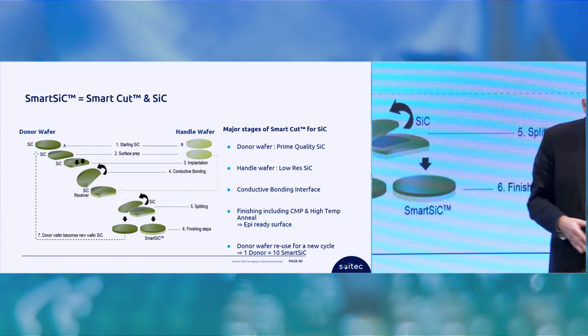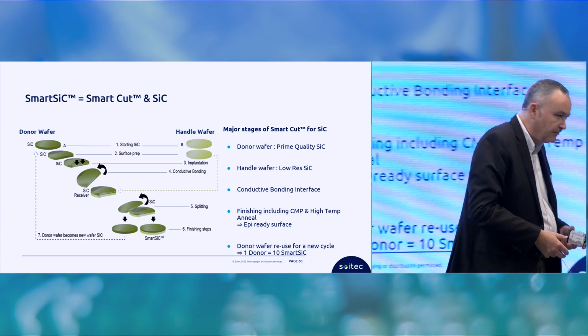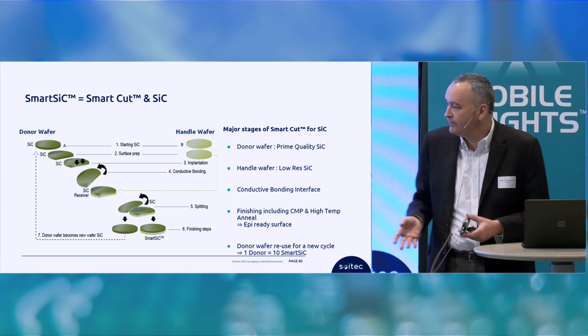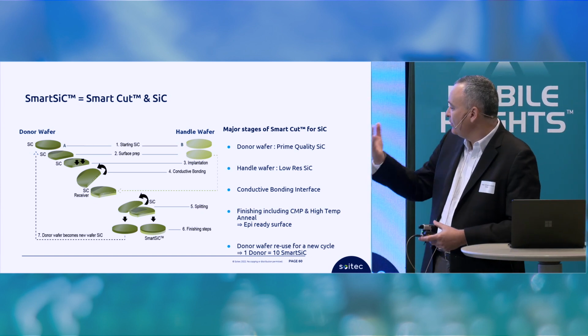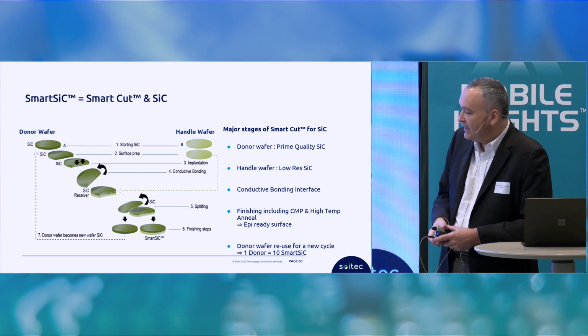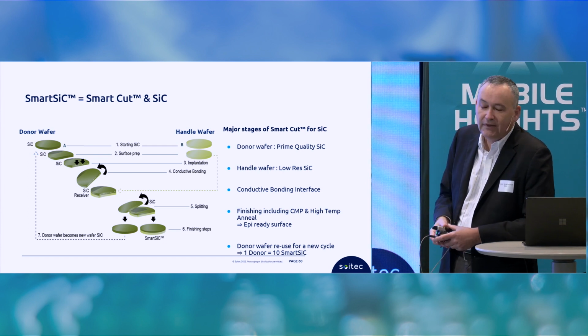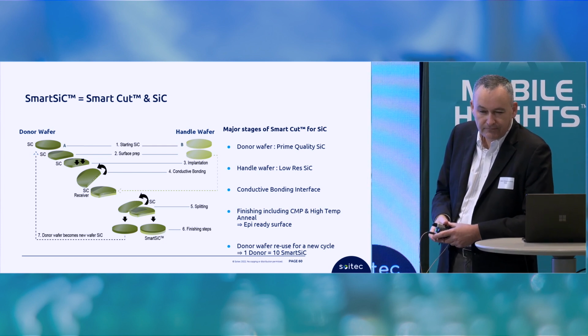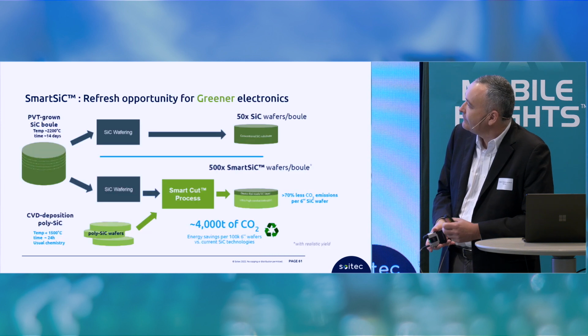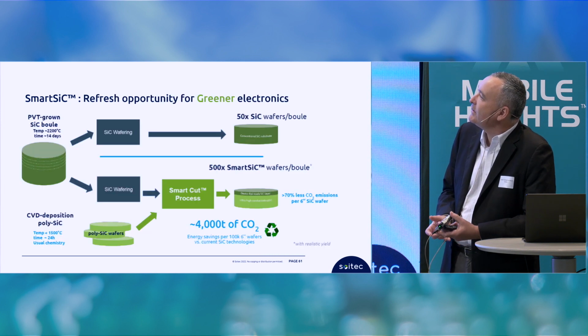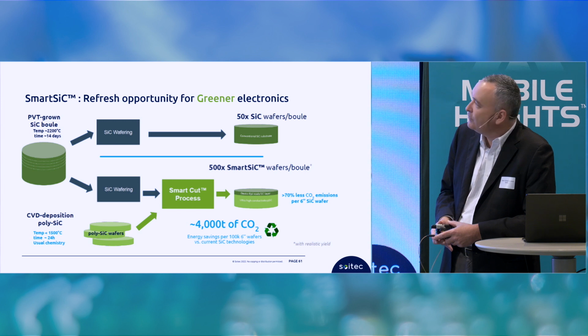We can refresh, and that's one of the key benefits of the Smart Cut, because with the refresh we can reuse the donor wafer several times, and typically with one donor wafer we create 10 SmartSiC wafers. 1 to 10. So this refresh is a great opportunity for the product to have a greener electronics.